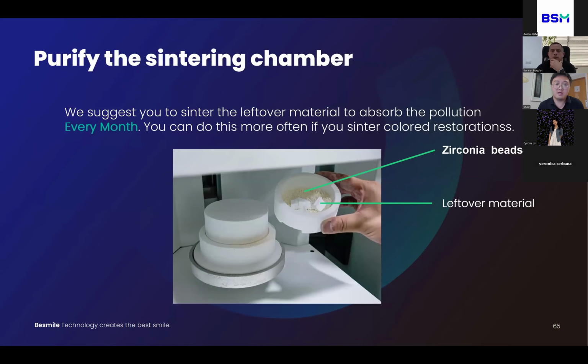Sometimes the customer may meet some special shade problems, like polluted color, such as greenish, yellowish or reddish color. This special shade problem might be caused by impurity in the sintering furnace. So we suggest the customer purify the sintering chamber by sintering leftover materials to absorb the pollution. In our furnace, there's a cleaning program. The customer can just use the cleaning program to sinter the zirconia leftover materials.